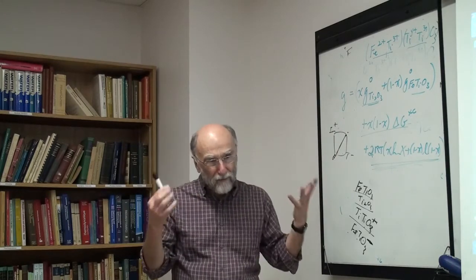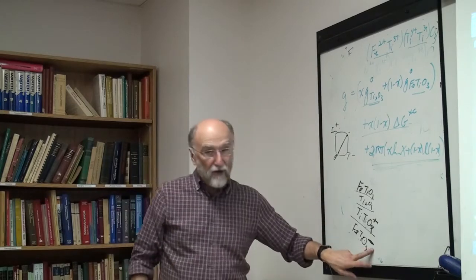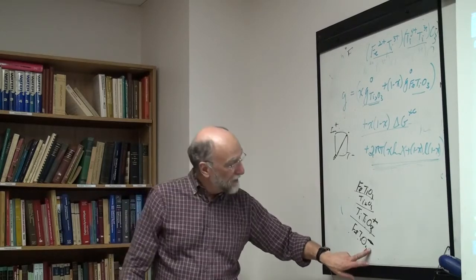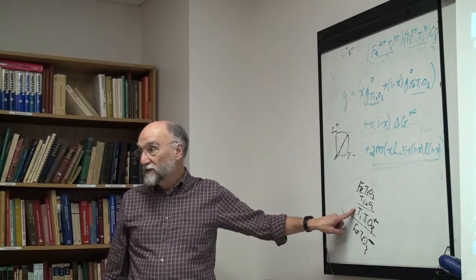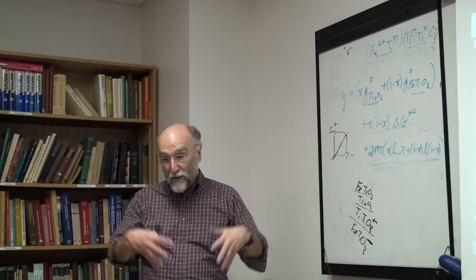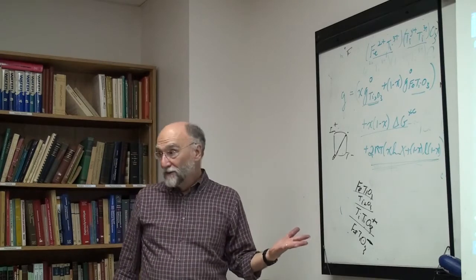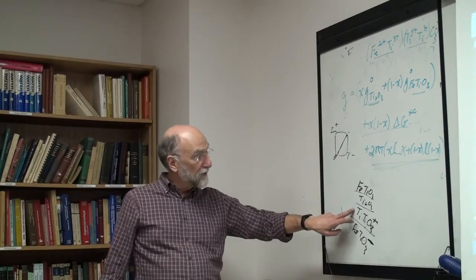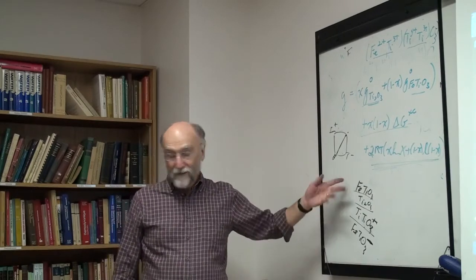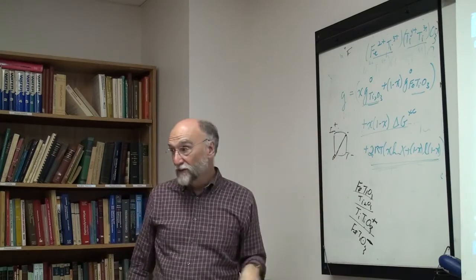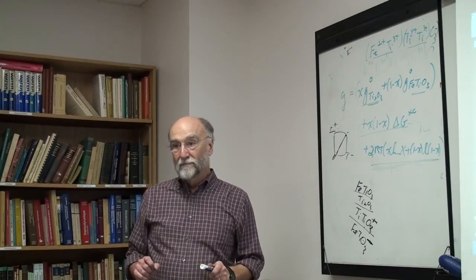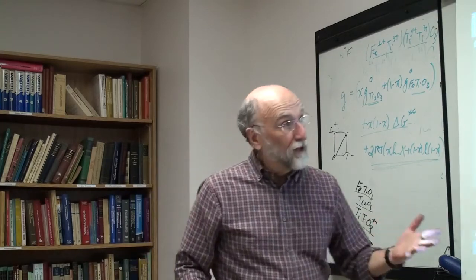It doesn't know from neutrality, but you're telling it the electron, if you like, is an additional component, and this end member contains 1 electron, and this component contains minus 1 electrons. And the total number of electrons in your whole thing when you enter your reactants is 0. This has 1 electron, this has minus 1 electron, so the sum has to be equal to 0. So it automatically just makes sure of that. But when you look at the mathematics, that's basically what it's doing here.